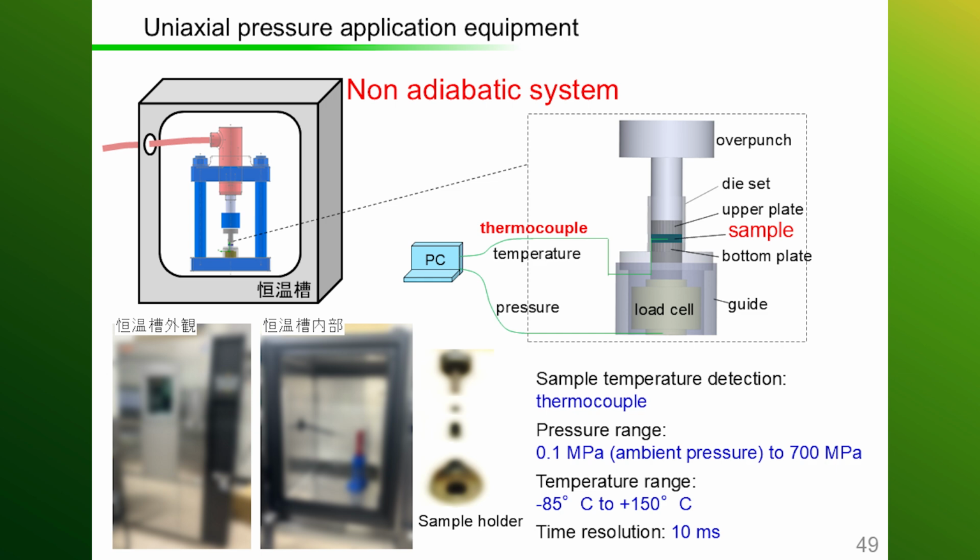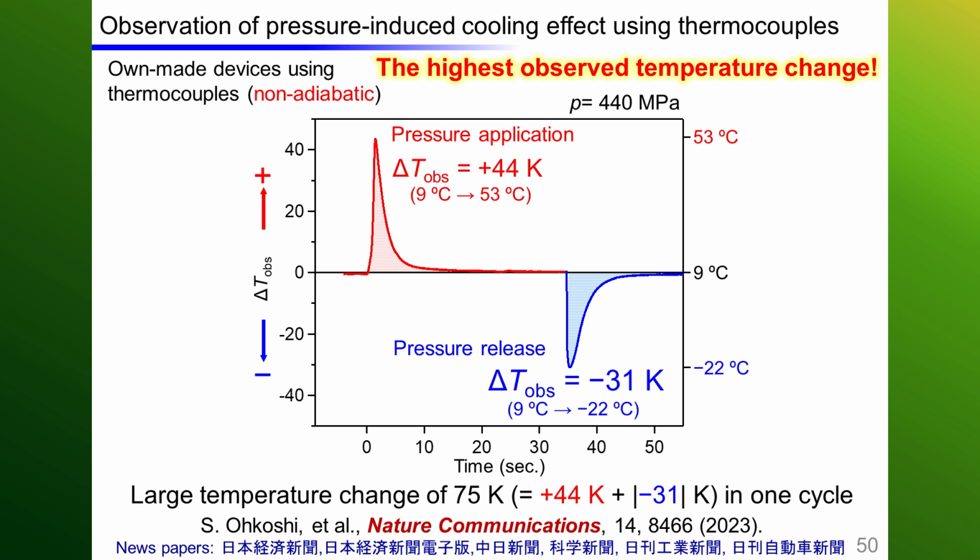This is, even written as roughly as this, something no one had ever seen before. This material also achieved a world record. So the 85 Kelvin temperature change I mentioned earlier is roughly what this should be theoretically. However, because the measurement was made with a device with such a simple structure, the measured temperature change was only about half of what it should have been. We would like to further refine this to produce results closer to the calculated adiabatic cooling temperature, as mentioned earlier.